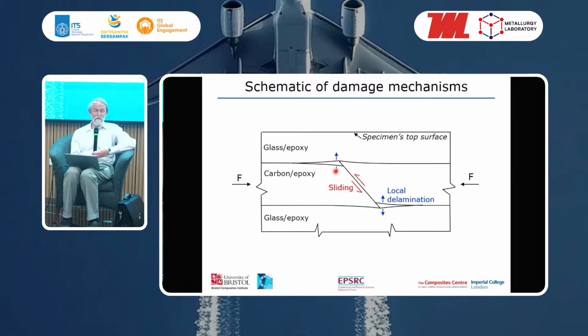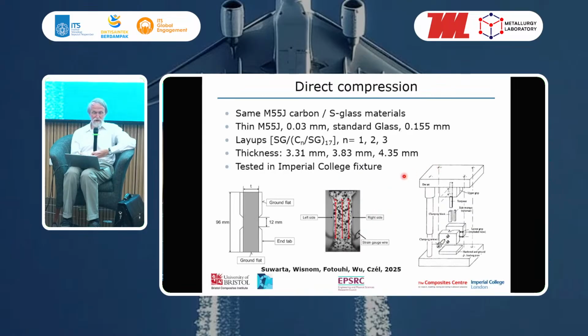But if we load it too far, then this delamination may propagate. But because these plies are thin, that propagation does not occur initially. So that's the schematic of the failure mechanism, and some very interesting results which Dr. Putu did on compression of these specimens here.